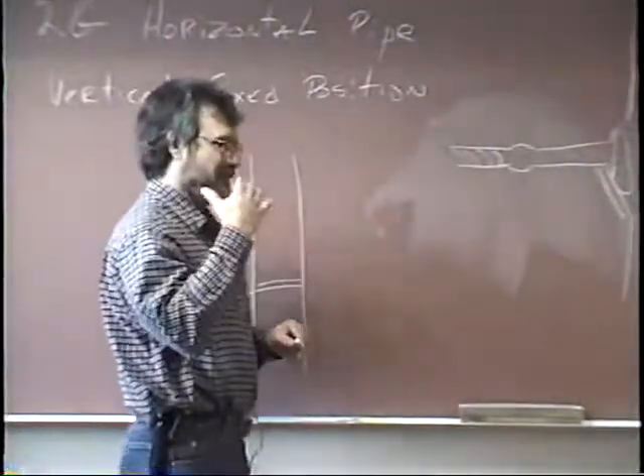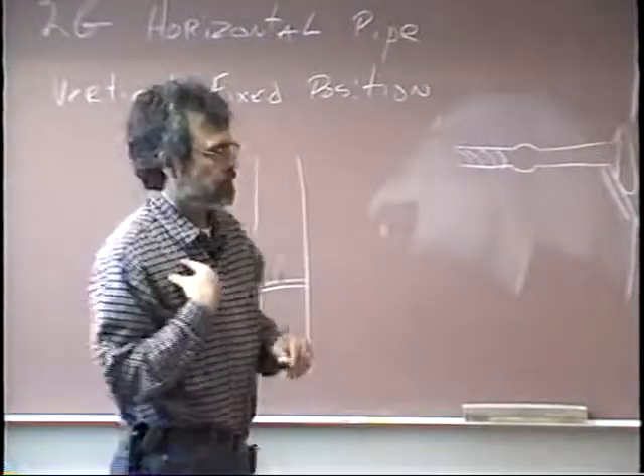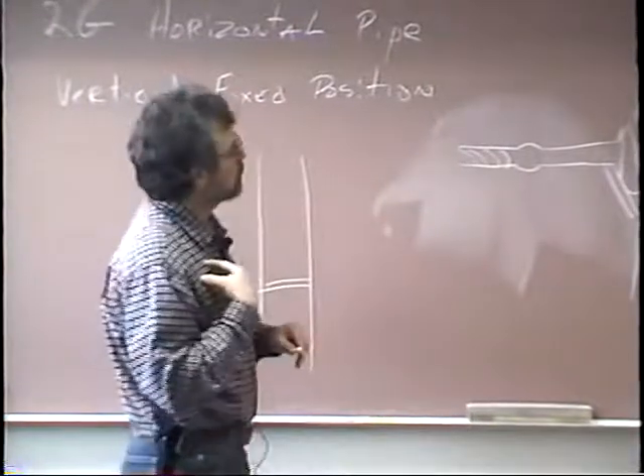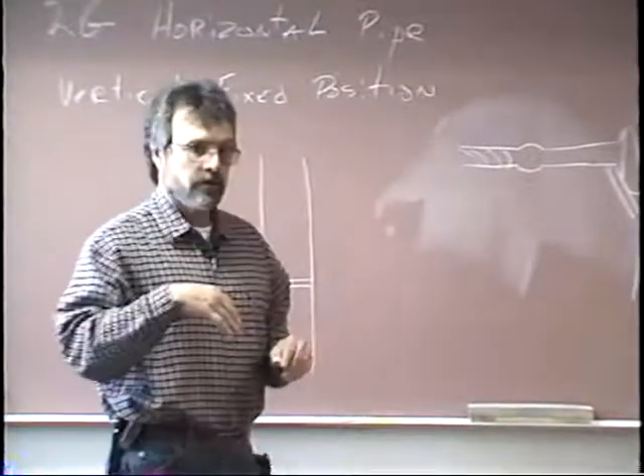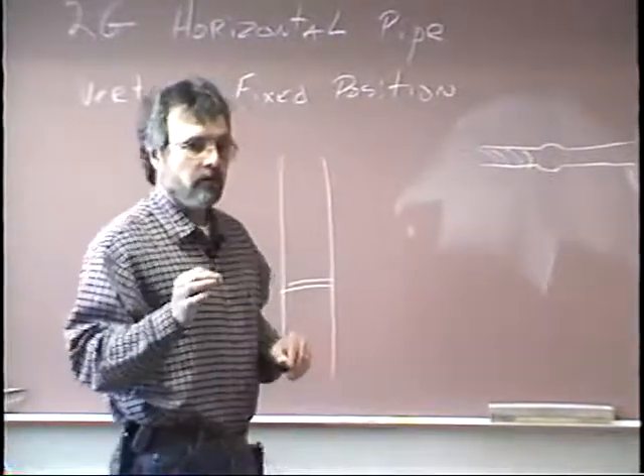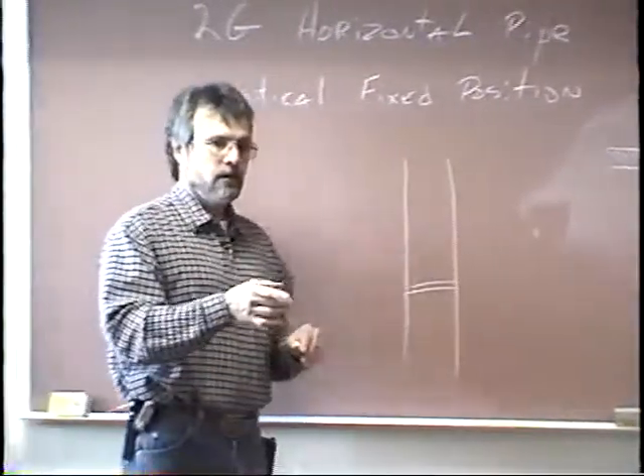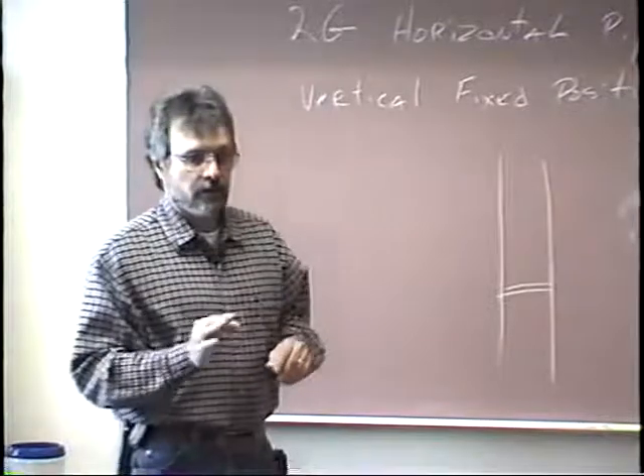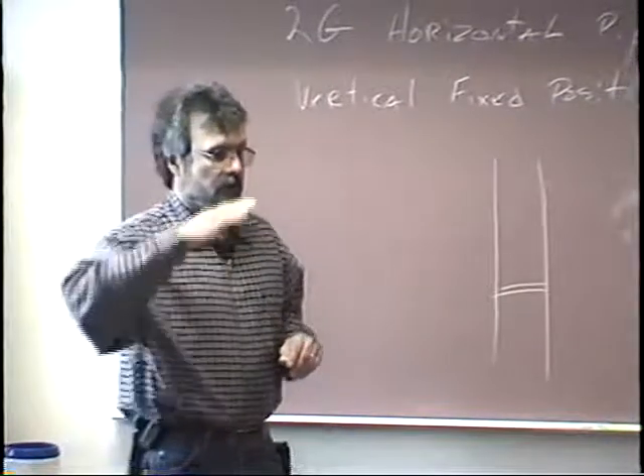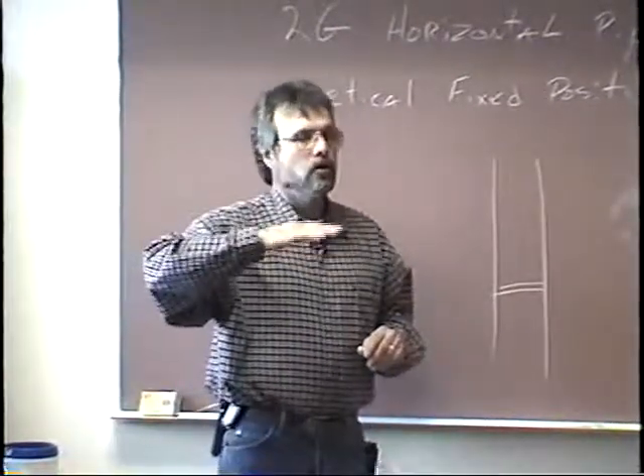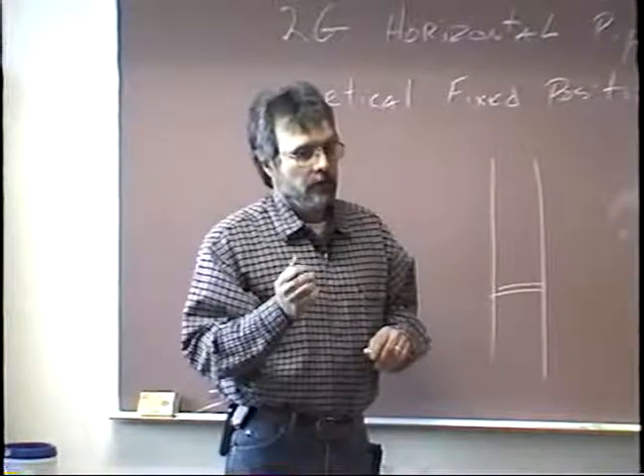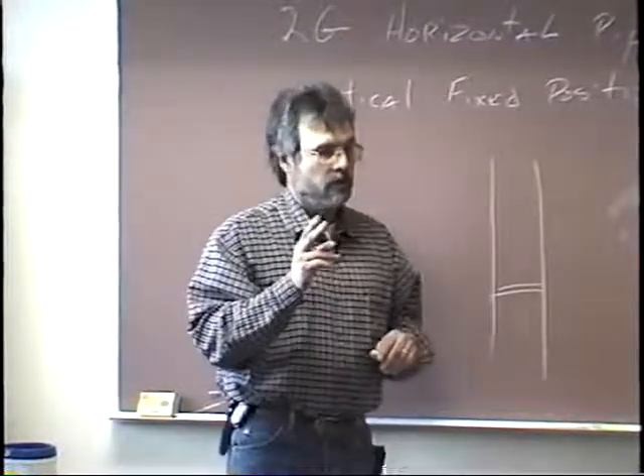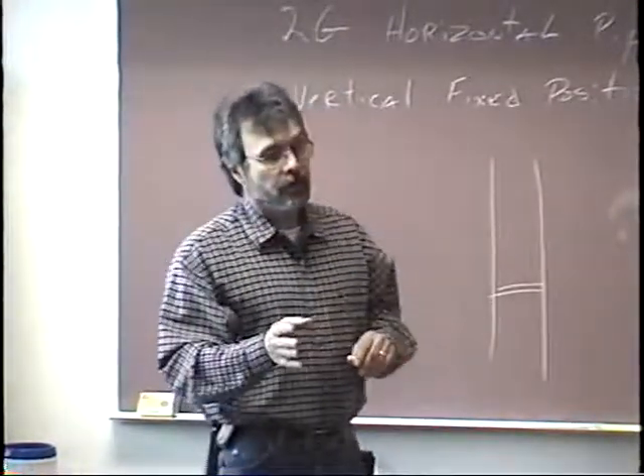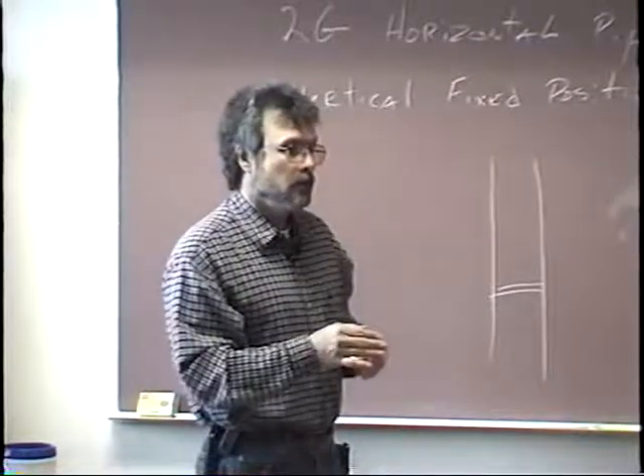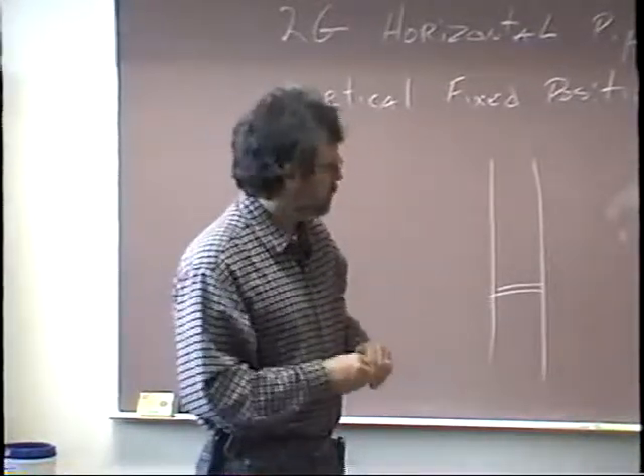Not only, well, in my view, from my experience in welding, the primary problem is internal undercut. I've failed more people on pipe tests for internal undercut than almost anything else. And that's simply because they'll either use the wrong rod angle or they'll have too high a current. Either of those two things can really cause you problems. You could have the correct current but be moving too slow and have that same problem.